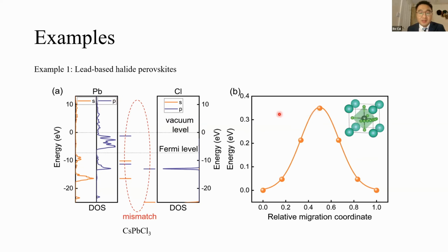It is about 0.35 eV. This result is consistent with previous results, and it also explains why we always observe ion migrations in halide perovskites in experiments.